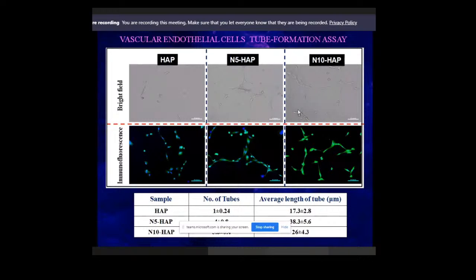So here we found that when you use these materials, there is more network formation among the endothelial cells in comparison to the normal HAp. But eventually what we observed is that N5 gives better results than N10. And then we also calculated the number of tubes, average tube length, and so on.